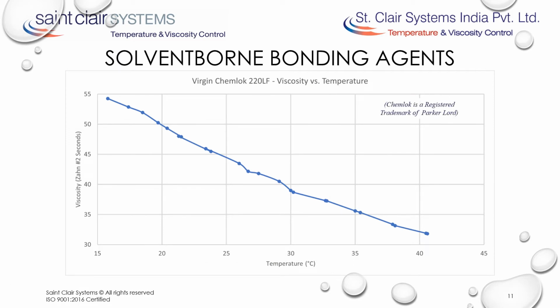For instance, here we see the viscosity temperature curve for Parker Lord's Chemlok 220, a common solvent-borne bonding agent as measured in St. Clair Systems India's lab. It's the typical curve we're all familiar with, the viscosity falling as the temperature increases. Though it looks like a linear relationship with a slope of approximately 0.9 seconds per degree C, when we apply a linear trend line, it reveals that, as with most modern coatings, this is actually an exponential curve. Another interesting fact is that Parker-Lord's DS3105 datasheet recommends that this coating be applied at a viscosity of 22 to 28 seconds, which is obviously below the minimum value shown in this dataset. This indicates that it must be diluted in order to be sprayed.